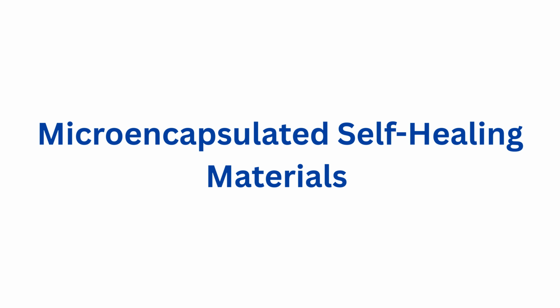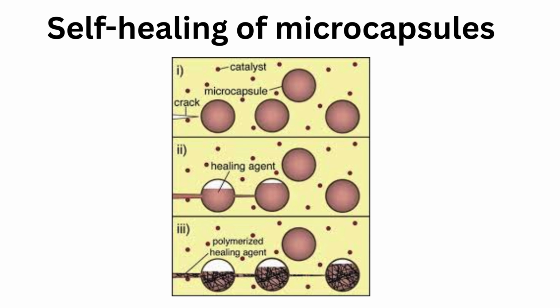Microencapsulated self-healing materials. This system achieves self-healing through ROMP, ring opening metathesis polymerization, which meets critical requirements including long shelf life, low monomer viscosity and volatility, and minimal shrinkage during polymerization. The ROMP reaction employs transition metal catalysts, Grubbs's catalyst, that exhibit high conversion activity while maintaining tolerance to various functional groups, oxygen and water. This reaction can polymerize dicyclopentadiene, DCPD, at room temperature within minutes, forming a tough, highly cross-linked